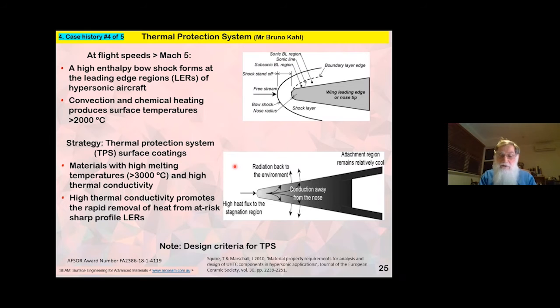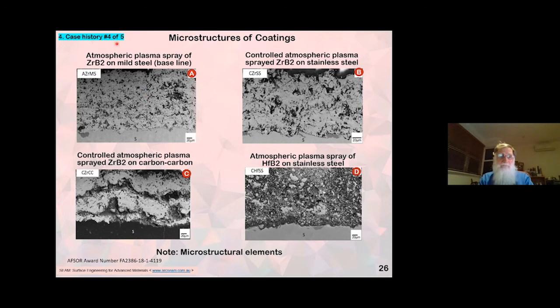We're now spraying a very interesting material called a boride. So we have a zirconium diboride or a hafnium diboride being formed in this case on a model material, either a simple mild steel or a stainless steel, so that we can eventually get to a carbon-carbon substrate, which is the real application, so that these very complex coatings can give a thermal conduction away from the leading edge. Zirconium diboride and hafnium diboride have very good thermal conductivities and good high temperature properties. And this is a project being sponsored by Wright-Patterson Air Force Base in the USA.